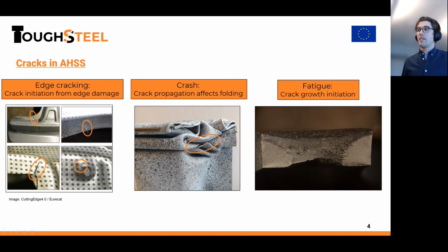Seen during forming operations, these cracks arise from the sheared edges as they are subjected to stretching, and they are, as David said, quite hard to foresee with conventional predictive tools. Another similar problem is cracks arising in crash components, which affects, like in this case, the foldability of an automotive crash box. Furthermore, the fatigue properties of high-strength steel are continuously being investigated, and fatigue failure is obviously also linked with cracks. What all these three cases have in common is that crack initiation and propagation have a huge influence on each component in each of these processes.